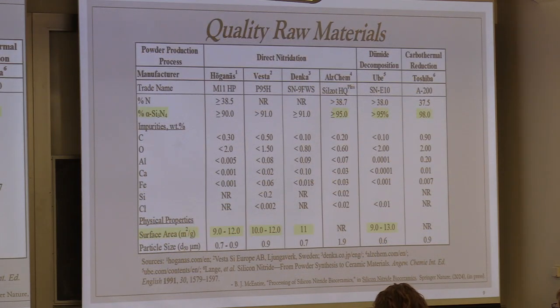So this is what the raw materials look like as they come out, and I've highlighted a couple of areas: the overall alpha silicon nitride content and the surface area of these materials. You can see that most of the companies who produce this produce it by direct nitridation, so they're just reacting silicon and nitrogen. As I mentioned, Toshiba is the only company I'm aware of that still has capabilities to do carbothermal reduction, even though Dow Chemical and a couple of other companies invested heavily in it, it never took off. And of course, Ube Industries has diimide decomposition. The important thing about the quality of the raw materials is they're very high purity and have very high surface area. They also have very high alpha phase, all of which are very important to produce good quality components that are readily sinterable.